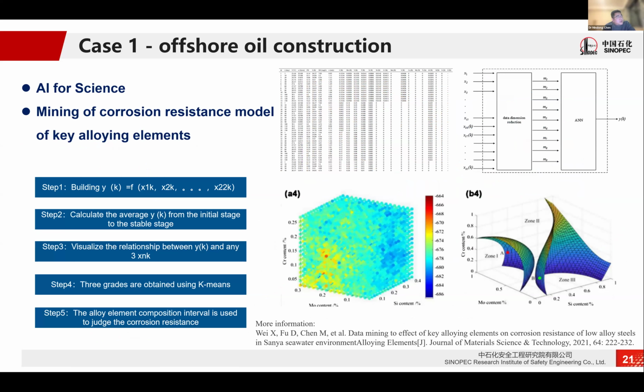And we established the steps. First step, we built the function in 22 dimensions. Step 2, we calculate the average value from the initial stage to the stable stage. Step 3, visualize the relationship between value and the elements. Step 4, 3 grades are obtained using k-means. And step 5, the alloy element composition interval is used to judge the corrosion resistance.